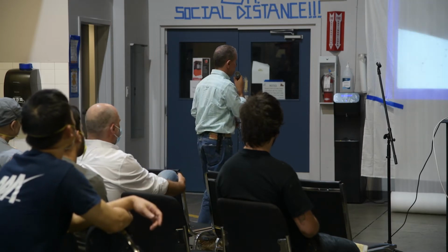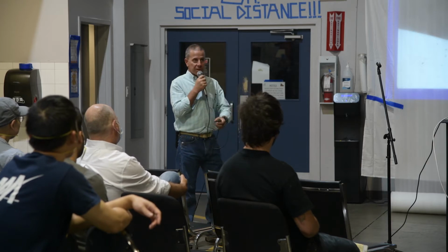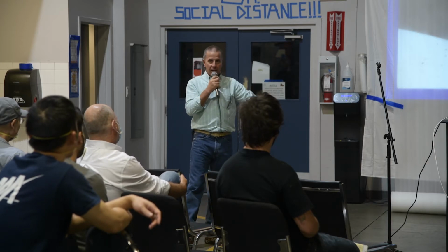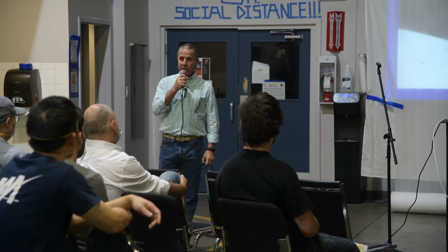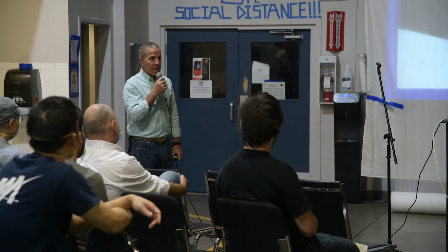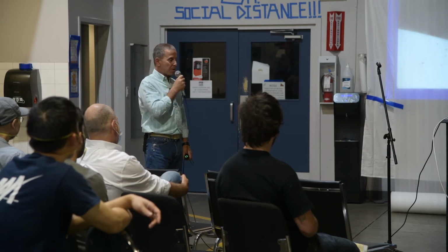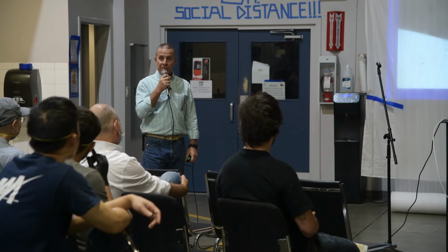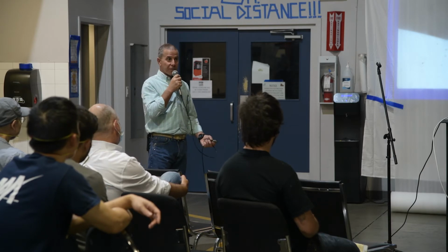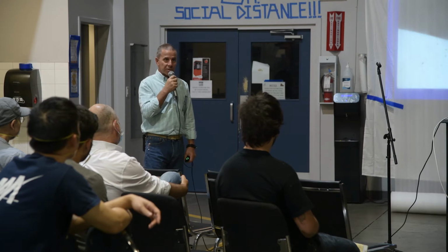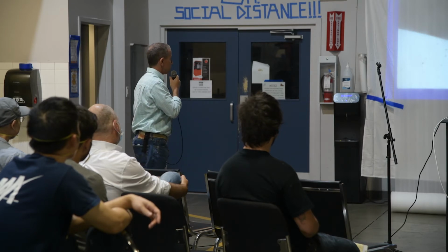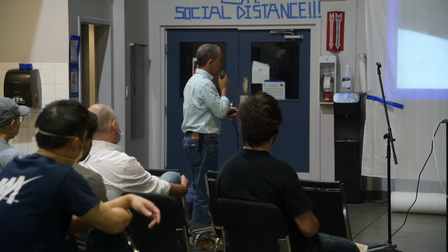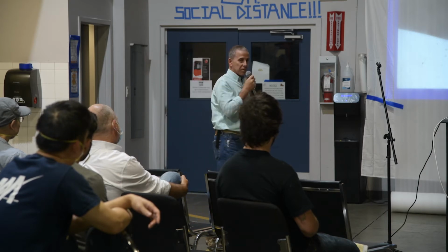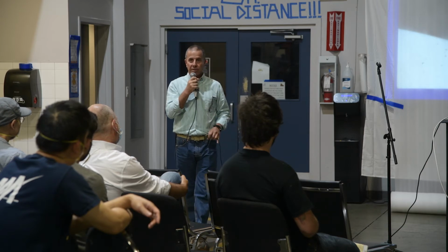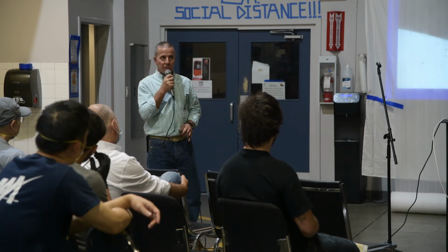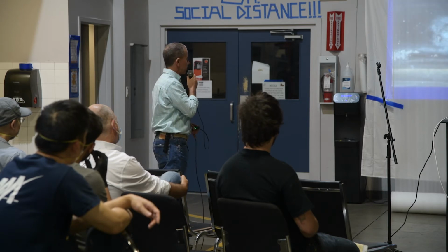Now here's a good example of this, a bronze sea strainer that is attached to an aluminum bracket. Again, it doesn't have to be submerged, it just has to be in a damp, high humidity environment. If that high humidity also has salt, sodium chloride ions in it, that's going to accelerate this process. It will occur in the presence of fresh water, but salt water accelerates it because of the conductivity of seawater. So again, you can see if you look closely, the aluminum is what's suffering, not the bronze. The least noble metal of the two is going to be the one that suffers as a result of this.